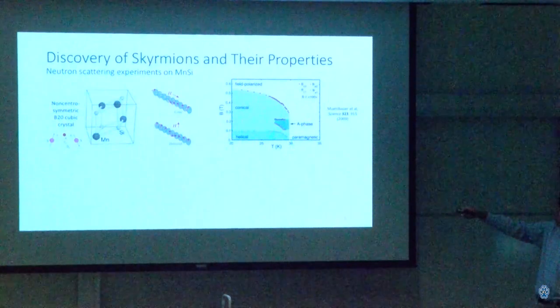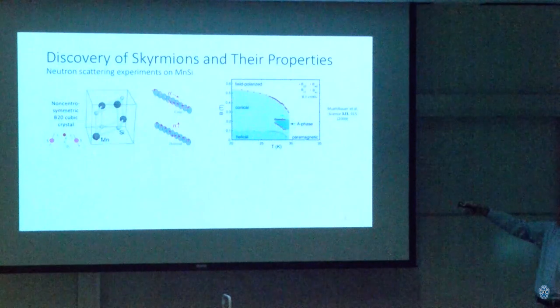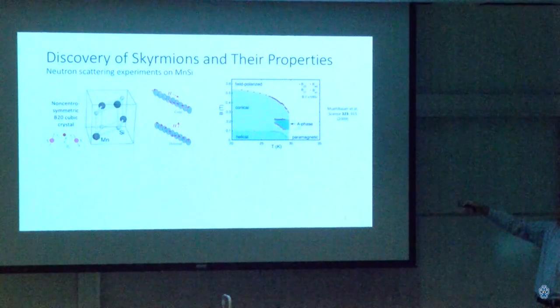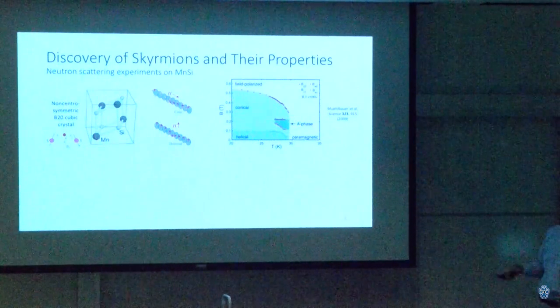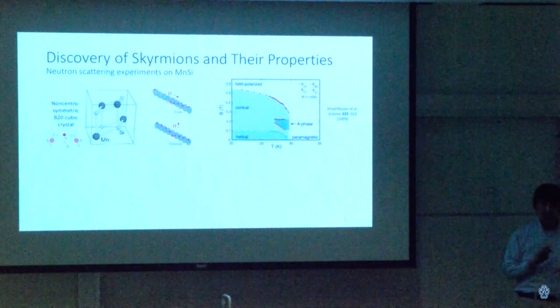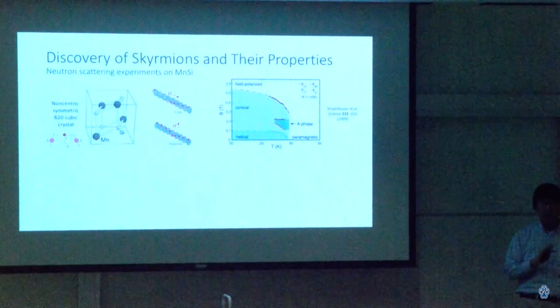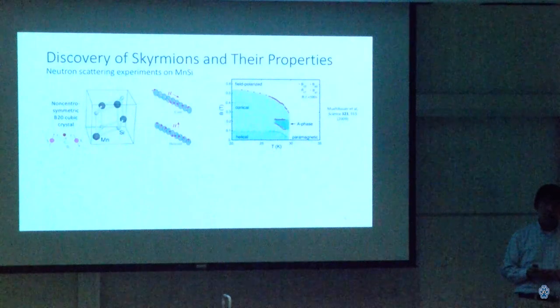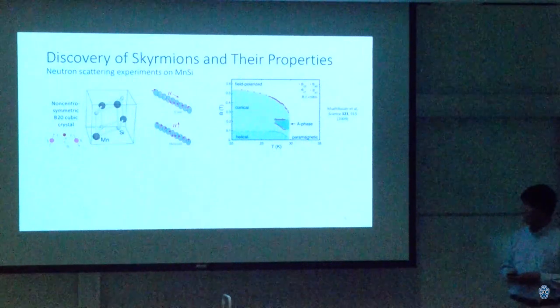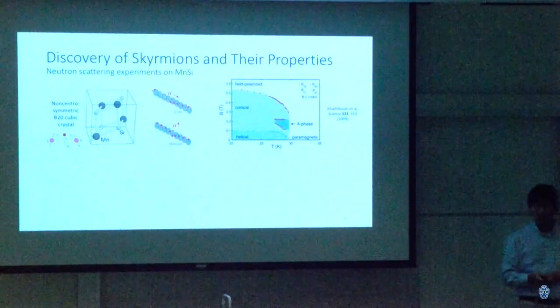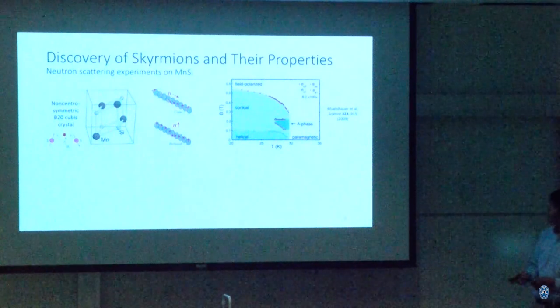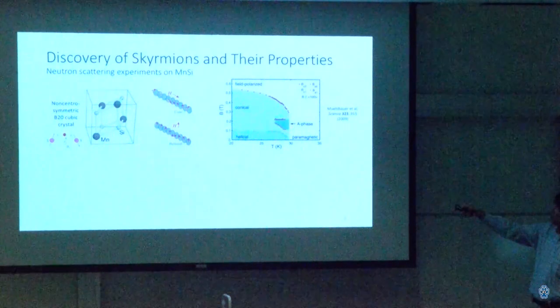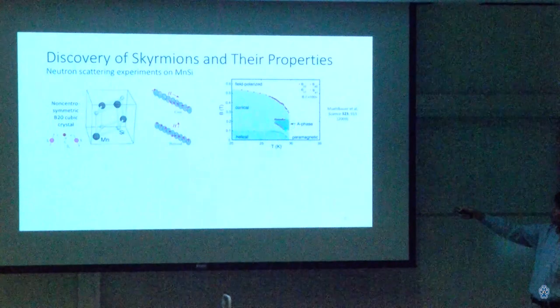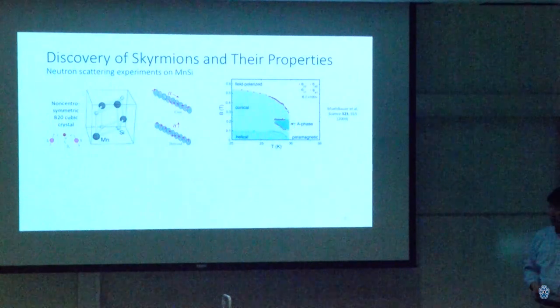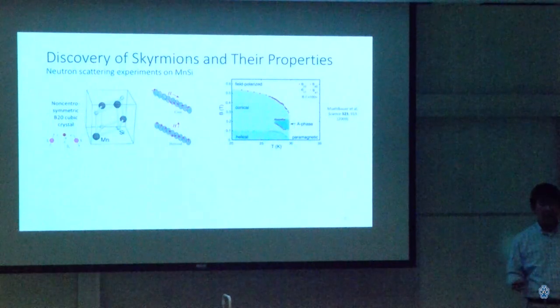But between 27 and 30 Kelvin, there is a little bit of a roadblock that for decades was unknown. It was clear that something was going on because the various different thermodynamic properties of the material were changing. The specific heat, for example, and the magnetization. And there were clear boundaries to this region, which people ended up calling the A phase. Not for any particular reason, just ended up having that name.